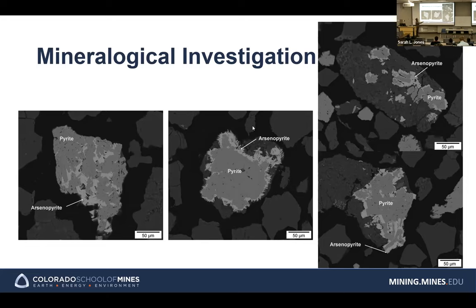And this big grain is muscovite, a clay material. And we have pyrite and arsenopyrite similar to this, and also pyrite and arsenopyrite here. In this case, even the arsenopyrite is inside the pyrite matrix. That's why we had a lower cyanide gold recovery. But after the biooxidation, we were able to oxidize those pyrite and arsenopyrite and liberate and expose the gold grain for the downstream cyanide process.